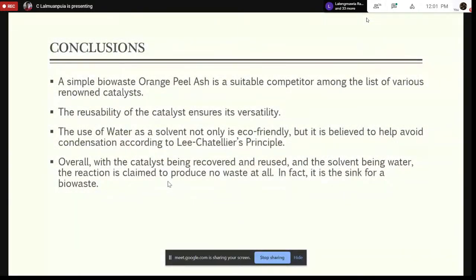With all those findings, we can come to the conclusion that a simple bio-waste orange peel ash is a suitable competitor to renowned catalysts. The reusability of the catalyst ensures its versatility. The use of water as a solvent is not only eco-friendly, but it is believed to help avoid condensation according to Le Chatelier's principle. Overall, with the catalyst being recovered and reused, and the solvent being water, the reaction is claimed to produce no waste at all. In fact, it is a sink for bio-waste. Therefore, this reaction is no doubt a greener route for the synthesis of aldol.